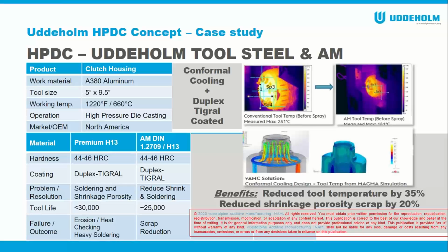So the only solution, being able to put cooling where you need it, because you cannot do so with a conventional water line, is conformal cooling. You can see that getting the cooling up near that gate allowed the solidification to happen at the right time and reduced the shrinkage porosity after machining, which was exposed previously. It was brought down well below 5%, and a no-brainer, an improvement in temperature. That goes without saying.